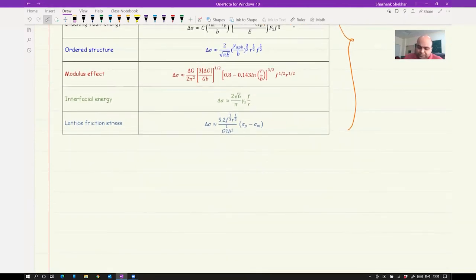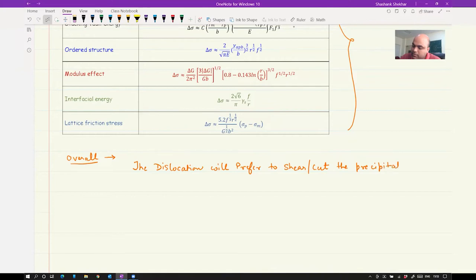Otherwise the concept remains the same. Okay. So overall, cutting or shearing of the precipitates will be preferred when the precipitate is coherent and small in size. So the dislocation will try to cut the precipitate when it is smaller in size and the interface is coherent. Okay. So overall, the dislocation will prefer to shear or cut the precipitate when it is small in size